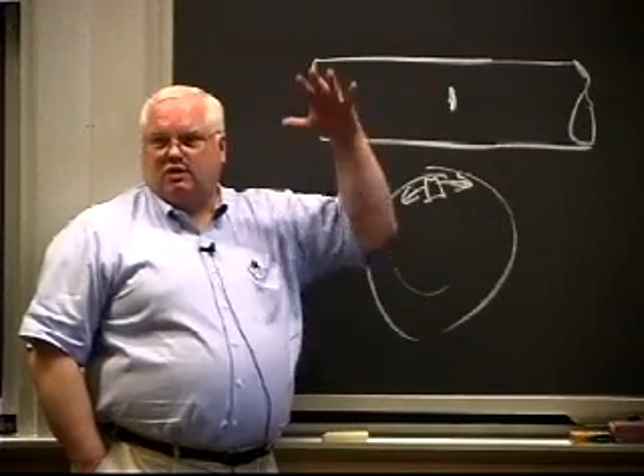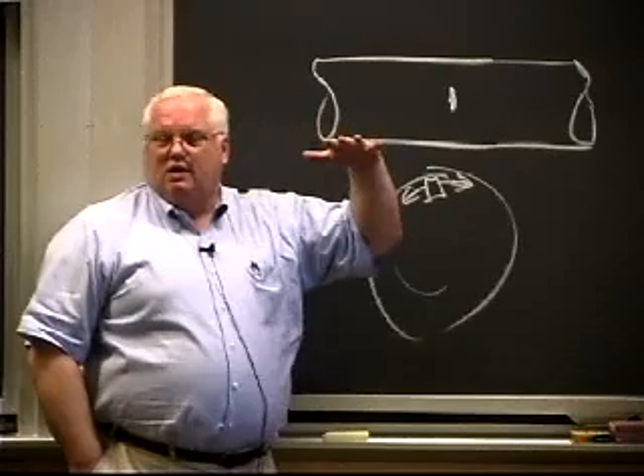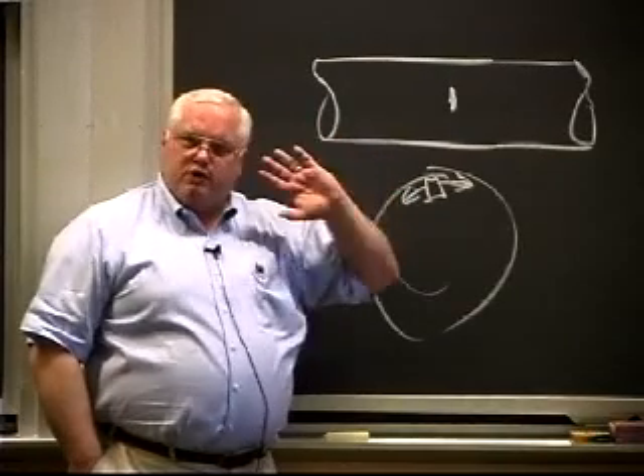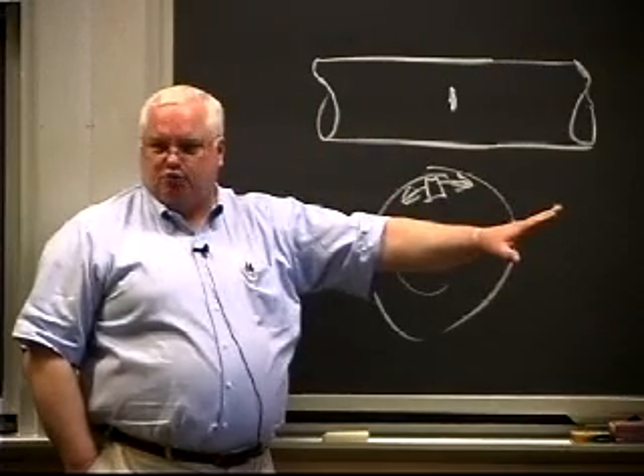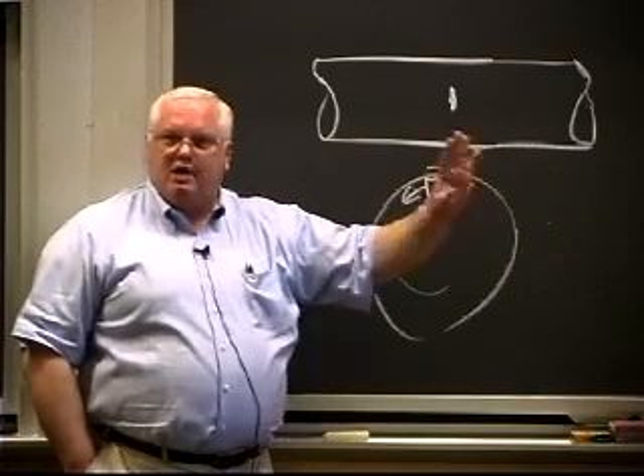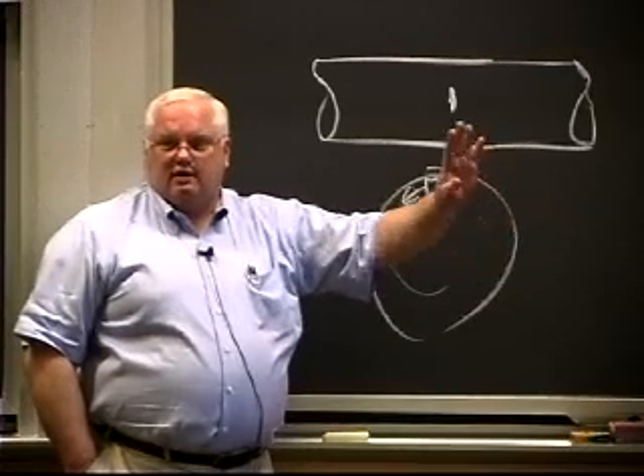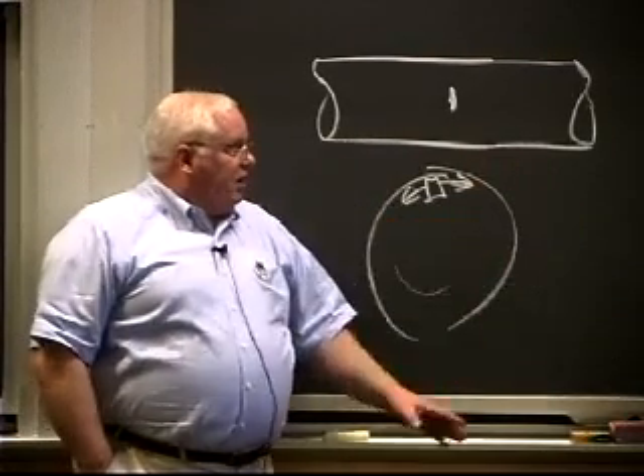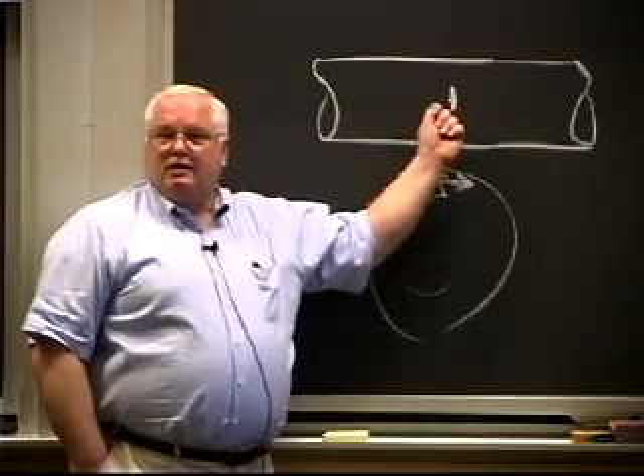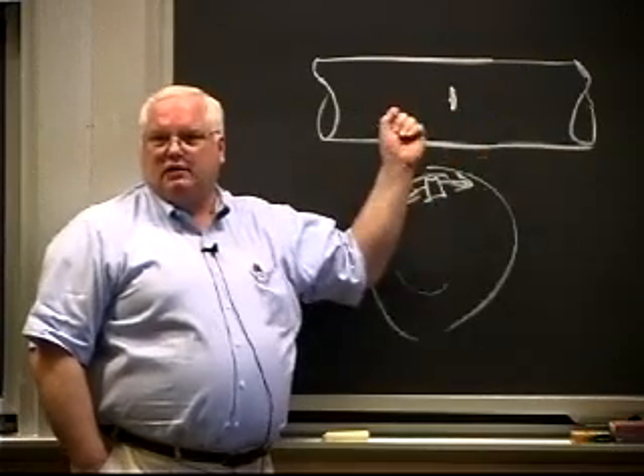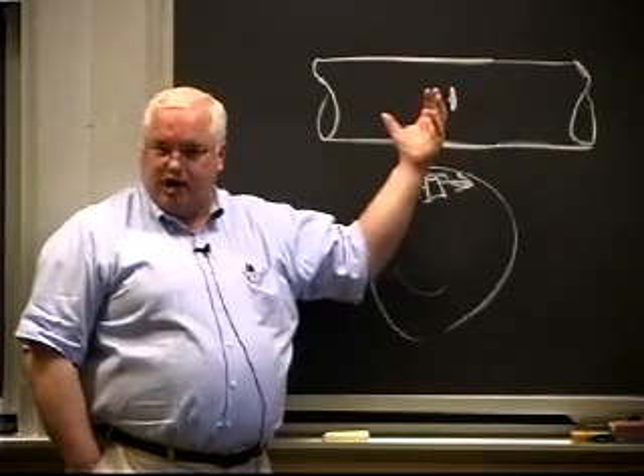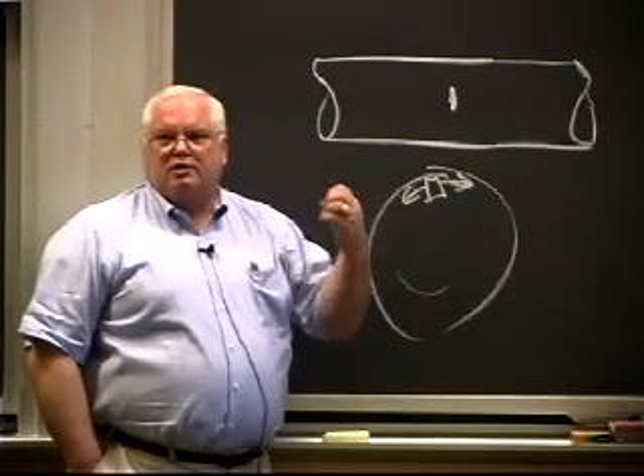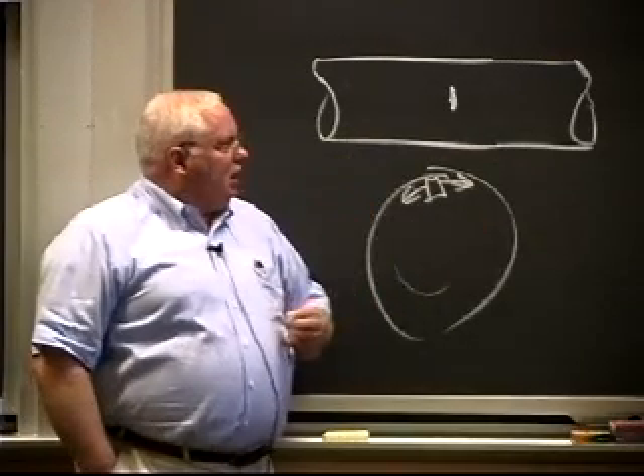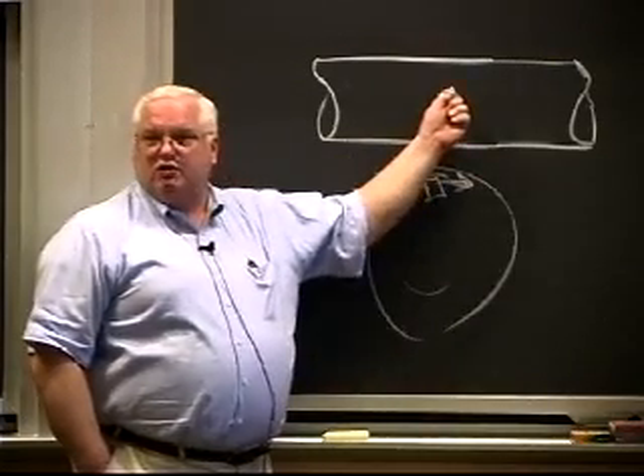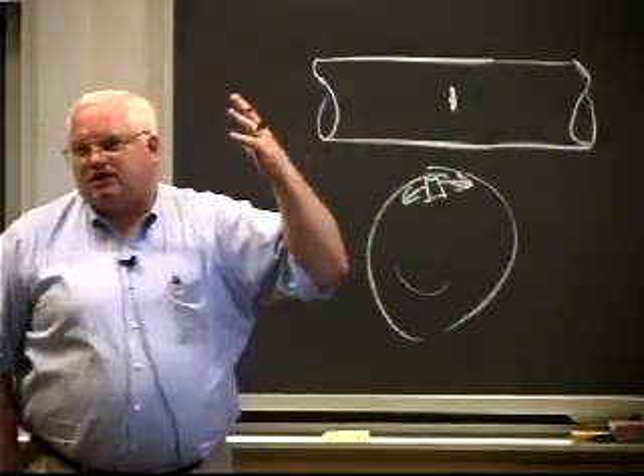Steel goes through its ductile brittle transition temperature somewhere around room temperature. Hopefully we make steels better and we get the ductile brittle transition temperature below room temperature and below 0 degrees Fahrenheit and sometimes below minus 100 degrees Fahrenheit. But they hadn't done all the good heat treatment. They were still forging this thing to get it to shape, and then they were going to do the good heat treatment that gives you a finer grain size and gives you a lower ductile brittle transition temperature. So this material was still brittle, even at maybe plus 100 degrees Fahrenheit or even plus 200 degrees Fahrenheit in the center.